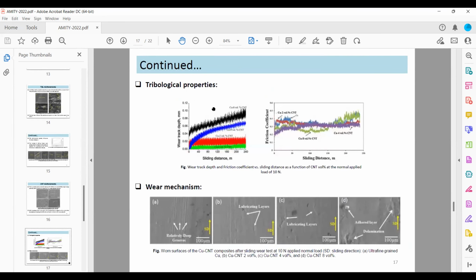The tribological property is good here, as the strengthening effect of CNT through the load transfer mechanism is occurring, and CNT also acts as a solid lubricant. So the wear rate and coefficient of friction decrease. And the wear mechanism here shows that without the addition of CNT, grooves are present, but after CNT addition, it forms a lubricating layer.